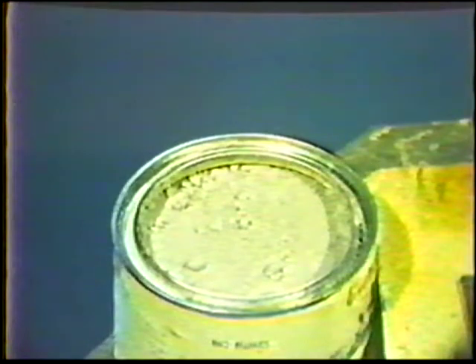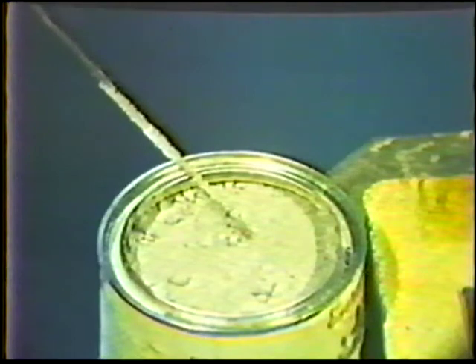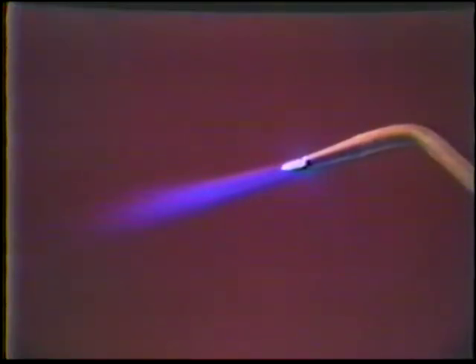The workpiece for this practice is made from 2 mild steel plates, tack welded together at each end to form a square groove joint with a 3/32 inch root opening. For braze welding, flux is needed for preventing oxidation and for absorbing impurities. A thin, even flux coating is applied to the filler rod by heating 2 to 3 inches of the rod, then dipping it in the powdered flux. The coating should be about 1/16 of an inch thick. The flame is adjusted so that it is slightly oxidizing.